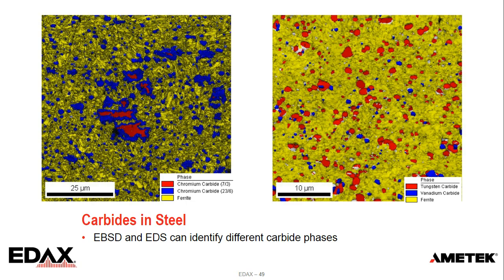The final one I'll take goes back to which polishing method do you use to get this data. I'd say most of these, or probably all of these, were collected with samples that were mechanically polished down to colloidal silica, either a 0.02 or a 0.05 final polish slurry. If you're interested more in that, we have saved webinars specifically for sample prep. We are starting to do more ion beam preparation to experiment with that, particularly for retained austenite, to see if that has an effect, but that's just work that's starting.